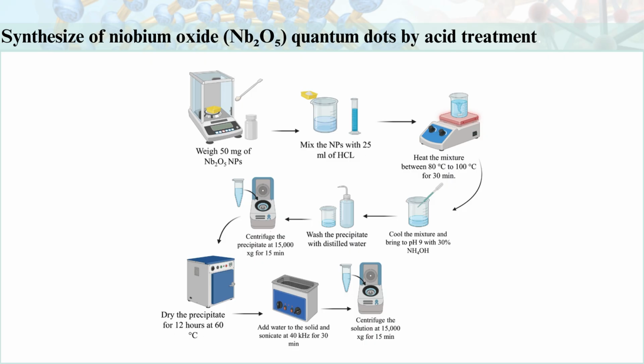For the synthesis of niobium oxide quantum dots, a chemical etching treatment was used, which consists of using a strong acid to degrade the surface of the nanoparticles and thus reduce their size. Therefore, previously synthesized nanoparticles were used.